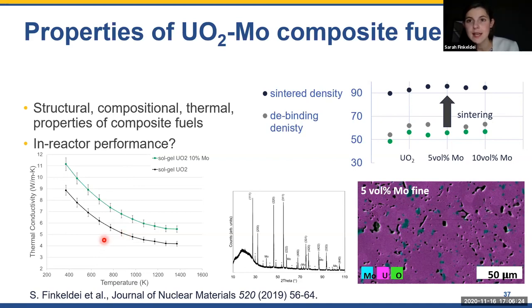So what we did is I fabricated also uranium dioxide, so you only see some data here. But I also fabricated a uranium dioxide pellet from a powder precursor, and we obtained a lower thermal conductivity for that and compared this to literature data. And I corrected the entire data to the same density, so the density is not the factor that causes the difference in our thermal conductivity from a sol gel feedstock versus a powder feedstock. So we are still not completely sure where exactly this is coming from.